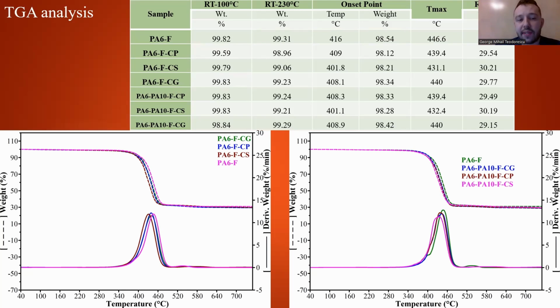Treated fly ash composites begin to decompose at a temperature of 6 to 15 degrees lower than polyamide 6F, and decompose at a maximum rate at a temperature of 7 to 16 degrees lower than the same polyamide 6F. The largest decrease is observed in the case of ash modified with a metal salt agent, while the silane treatment showed the best thermal stability compared to the other treatments. And also the residue at 750 degrees correlates with the amount of inorganic material present in the composites, which is 30% for both series.